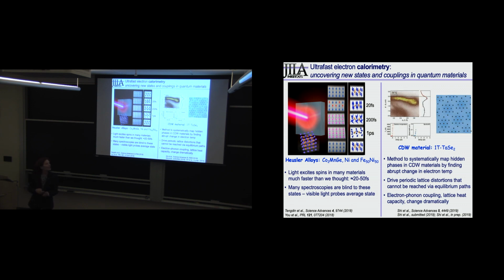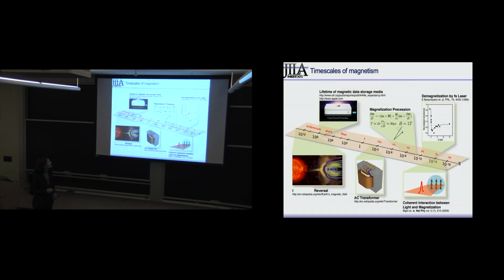But what we didn't realize is that here in 2D materials, ultrafast lasers have an advantage, because the cross-plane phonon modes are very, very weakly coupled, for about a nanosecond, you've made the material more 2D-like, so you can actually explore the couplings in that 2D material and actually drive it into new phases. I probably won't have time to talk about it, but it just shows that there's a number of interesting things we can look at with ultrafast lasers.